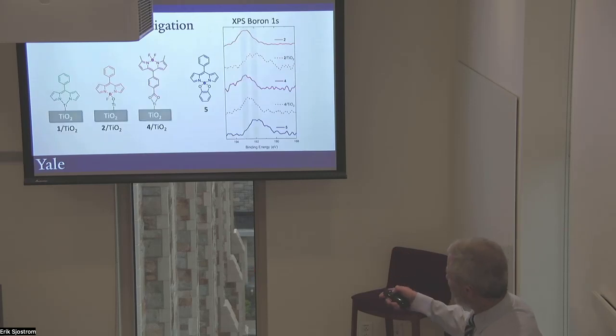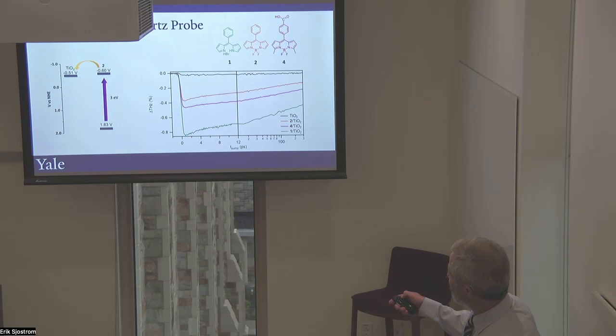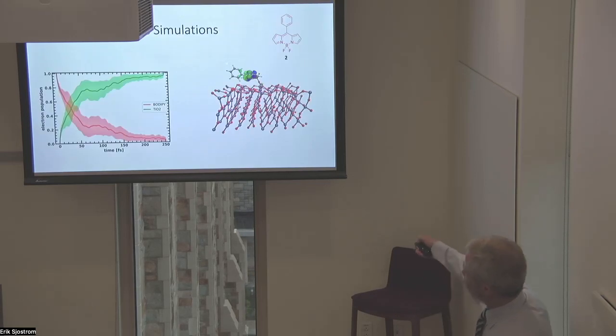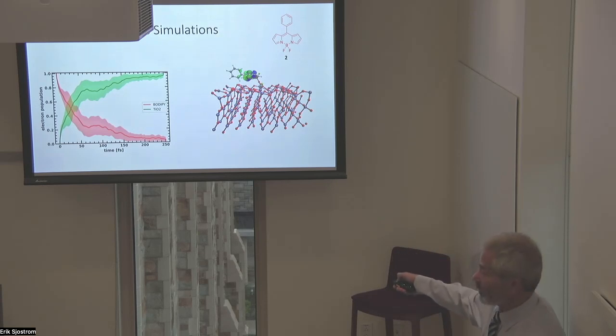Yeah, maybe I should go ahead to this picture. This is the quantum dynamics simulation. What you see here is that the excited state orbital is localized on the part of the molecule that's near the surface. That's a good thing because it means there's good coupling between that orbital and the surface conduction band orbitals. So you get very efficient electron injection, which is why this happens on a very fast, tens of femtoseconds time scale.